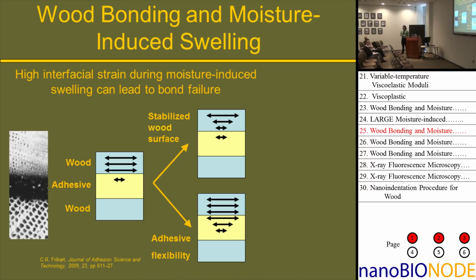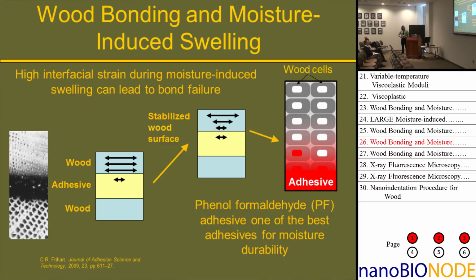So getting back to our wood adhesive bond lines, there are two ways that the strain mismatch can be accommodated. One is that you could have a flexible adhesive, but I don't think you want to build a house out of something with a flexible adhesive that's going to creep over time and fall apart. The way that more structural adhesives work, we believe, is that they actually stabilize the wood surface. When you go down to that interface, you're down at the cellular level, and it's believed that adhesives need to both penetrate into the lumens next to the surface and also infiltrate into the wood cell wall. One of the best adhesives out there right now is phenol formaldehyde.